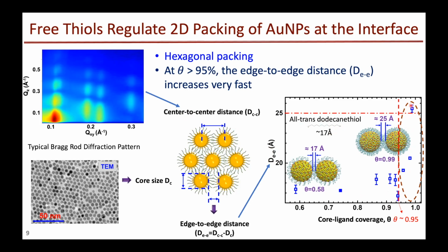I want to note that at very high concentration, the separation between particles is smaller than two stretched dodecane thiols, meaning interdigitation is happening, which makes the particles strongly bound.